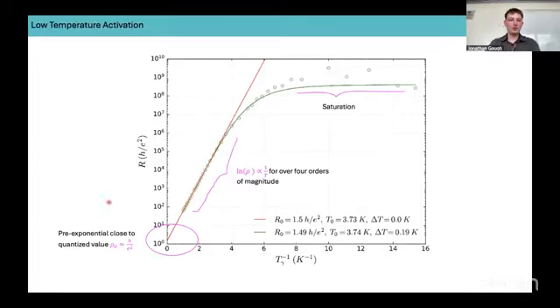So like I mentioned before, we observe in our samples this prefactor close to this quantized value h upon e squared, which is obviously very unusual, as you expect, given variable range hopping, that the prefactor would depend on the properties of the phonons, the lattice properties. However, it's extremely unusual this takes the quantized value independent of the materials, so different lattice properties. It always takes this universal value. I should mention before that this curve is calculated within the ohmic regime when the applied voltage is very small.